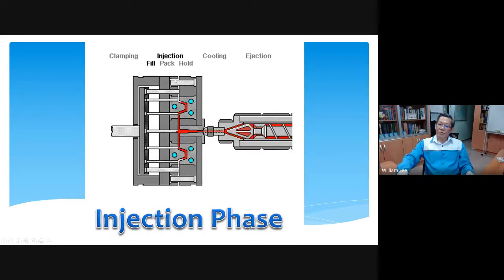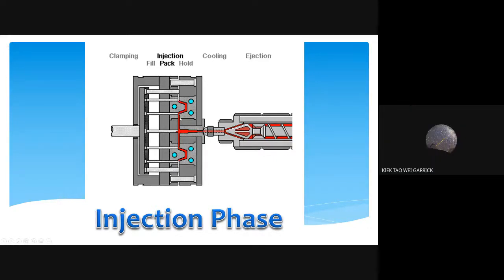When you pack, you are trying to squeeze in more material, and therefore, you will build up a tremendous pressure inside the mold. This pressure we call the cavity pressure, because it is exerted inside the cavity here, and it will try to expand the cavity, and sometimes it can force the plastic to flow out. This is called the backflow. If the plastic from the cavity flows back to the runner system, you will end up with some short molding. Therefore, at the same time, you need to hold it. Hold comes from your injection system here, whereby you need to prevent the backflow. So remember, during the packing, we only allow one way. We don't want the plastic to flow back.